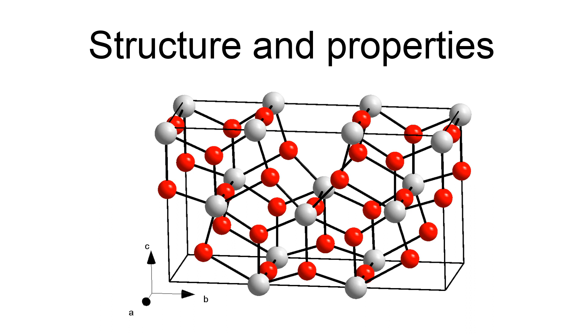The difficulty in forming material with a uniform structure has led to variations in its reported properties. Like many metal oxides, Ta₂O₅ is an insulator and its band gap has variously been reported as being between 3.8 and 5.3 eV, depending on the method of manufacture. In general, the more amorphous the material the greater its observed band gap.